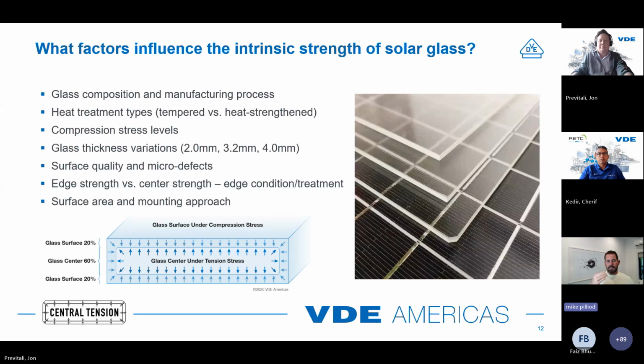And then at the systems level, when you go through how the glass is mounted, like I mentioned, glass breaks in tension. So how it's mounted, for instance, a cantilevered edge or where there are support structures. For instance, also if there's a hole in the glass on the backside for junction boxes, those edge conditions, if you look at the graphic on the side, those are ground surface edges. So you're cutting glass and you're grinding it. From a glass science perspective, you're inducing a bunch of flaws. Your goal of grinding is just to get it smooth enough and defect free enough that it has strength when you go to mount it in the solar module.